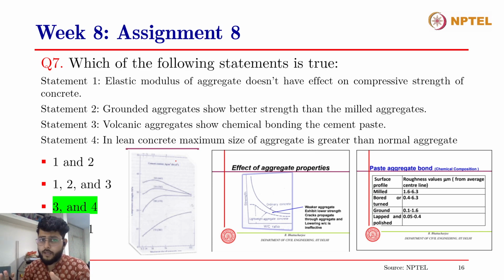And elastic modulus of aggregate, how does it affect the strength of concrete? When you apply a certain load to a concrete specimen, this load is being shared by, as I mentioned, all the distinct phases. So if you have some material that has a higher elastic modulus, that will also take a higher share of the load as compared to the other phases, and therefore, if you have an aggregate with a higher elastic modulus, the load being taken by all the aggregates as a whole will be higher, and that will in turn increase the total overall compressive strength of the concrete as well.